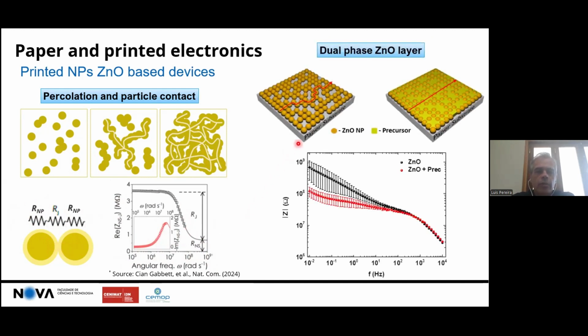And so we see here, for instance, that if you just put the particles on the top of the substrate, you may have to rely on the contact points they made. But you have also another approach that we developed some years ago, that is to fill these spaces, playing with the mixture of zinc oxide nanoparticles with a precursor.